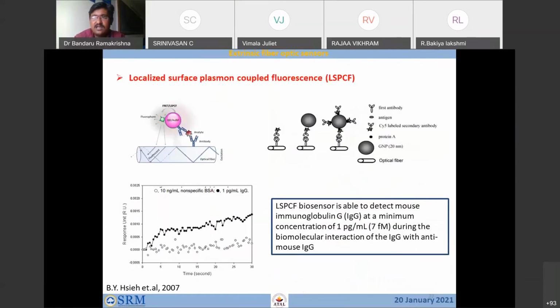And look at this, the other technology where people use quantum dots. Why do we use quantum dots? Because after a particular high concentration of fluorophore, fluorescence quenching is happening. Instead of quenching, we wanted to enhance the fluorescence emission. People have tried this with quantum dots. What we do here, the quantum dots are absorbing the light from the fiber and then delivering that light intensity, that energy, to the fluorophore molecules, and they will brightly appear.